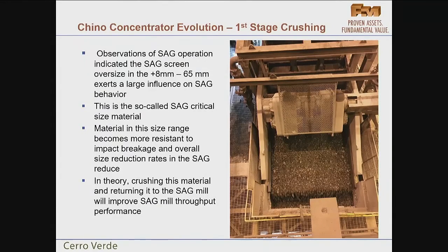Here, if you're looking at the photo, you see what is known as the SAG screen oversize, also known as the SAG mill critical size material, the +8 millimeters, -65 millimeters. The problem with this material is it doesn't break down so well in the SAG mill. The grinding rates reduce, and it just goes round and round, and affects the kinetics of the SAG mill pretty significantly. In theory, if we could crush this and return it to the SAG mill, it would improve the mill performance.